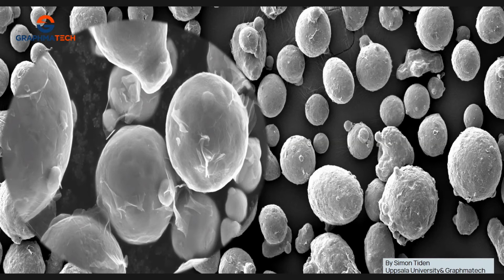However, this process is super exciting, but it's also challenging, because if you mess up any factor, you might oxidize the metal. You know, metal powders are quite sensitive to oxidation. And then you try to improve something by graphene technology, but you create trouble somewhere else, which is a byproduct of oxidation. These micrographs were taken by our PhD student at Uppsala University, Simon Tiden. As I will present later, results were also generated by him.